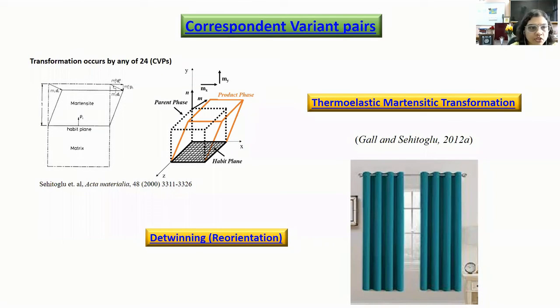So whichever way we are applying, if there is one particular grain which is achieving the highest value of the resolved shear stress, which exceeds the critical value that is required for the transformation, then only the transformation can happen. While we are doing the experiment, we can do it in any direction of our requirement.